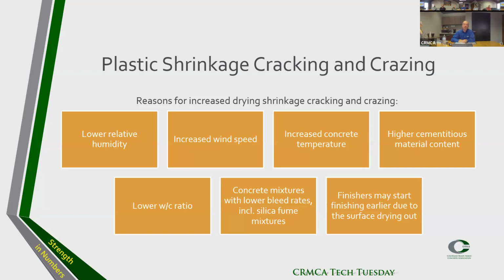Lower water cement ratio tends to go with higher drying shrinkage, cracking, crazing. Concrete mixtures with low bleed rates, silica fume mixtures, some of the new ternary blends that are coming out, have really low bleed rates, and we have to be very careful about shrinkage cracking. I'm going to mention that later on when we go through some graphs about when we need to cure and when we may avoid the curing. Generally, one of the things we see is that finishers start finishing too early because the surface is drying out and they think that the concrete is ready to go on, but it's actually not there yet.